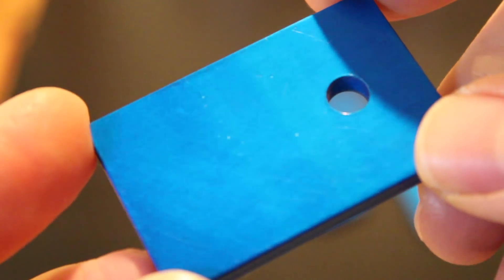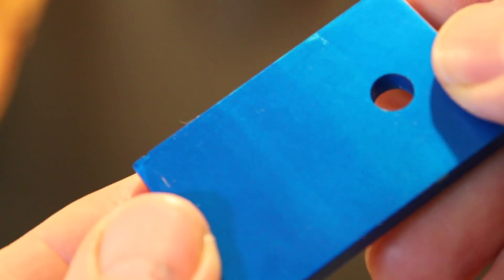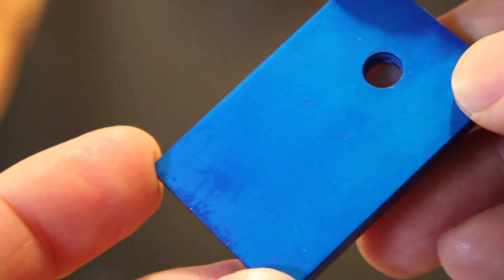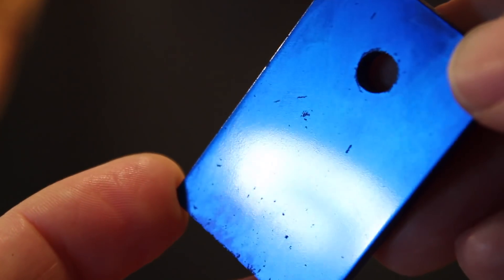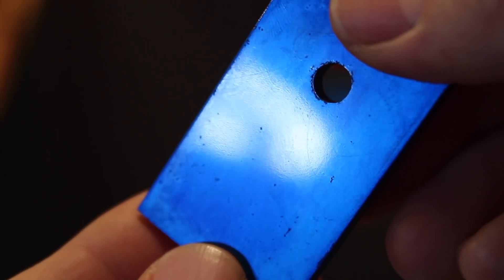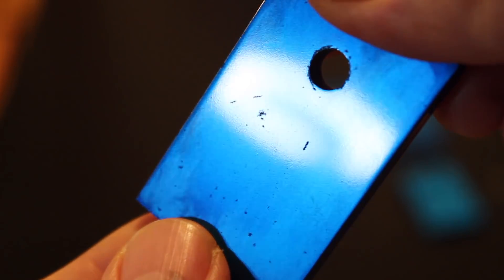The last two samples are the ones that I sanded. This first face I sanded to 600 grit and the backside to 1200. The banding is from a failed dye time test. This face is the 2000 grit. The holes, the pitting, came from trying a copper wire which did not work. And this surface is the 2000 grit and polished. And again that pitting I think is from that copper wire. And also higher amperage which I think was not good.